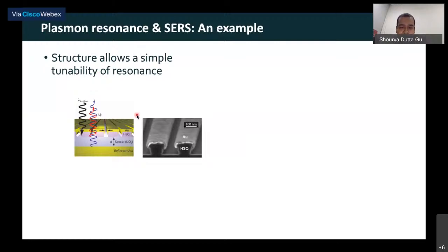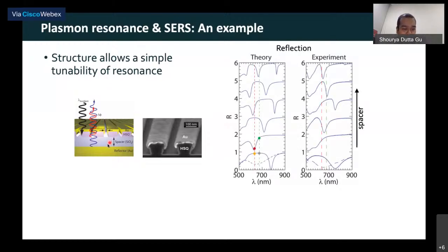Now if I look at the reflection as a function of different values of this spacer of SiO2, that is shown here. So the left column is basically the theoretical calculations, and the right column are basically the experiments. So the horizontal axis is the wavelength and the vertical axis is reflectivity. Now as I change this spacer from 100 nanometers to 700 nanometers, I see that the reflection actually changes significantly, right? Now these two dashed lines that I have correspond to the laser excitation wavelength and the laser emission wavelength for the Raman process that I'm looking at, right?